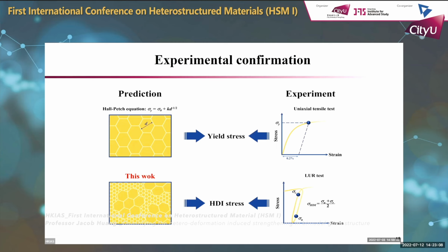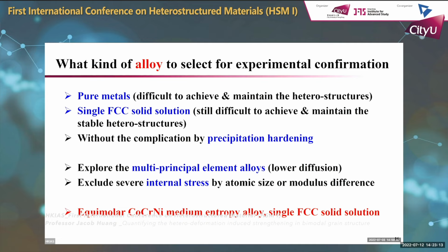We need to ask one question. What kind of alloy should we select for our experimental confirmation? Well, in previous studies, people used pure metals, like pure copper or pure titanium. But in our study, we found it is difficult to achieve or maintain such a heterostructure over the processing or over the tensile straining. So next, we considered a single phase like an FCC solid solution. Still the same thing happened. It's still difficult to achieve and maintain the stable heterostructures,